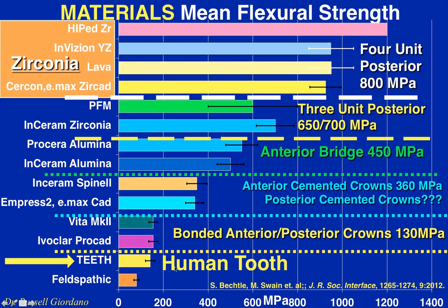What's also very interesting is that if you start looking in the literature and your criteria for materials is just strength, human teeth are not sufficient with respect to strength to be used in the mouth. So the conclusion that we must draw is that we must extract all teeth and replace them with titanium implants, because we all know that implants are much, much more reliable than teeth. At least that's what I hear from the implantology people and at the school. Of course, the endodontists have a completely different opinion. They think we should save every tooth. The periodontists who used to like to save teeth now are in favor of ripping them out and replacing them with implants. So if we use our strength criteria, human teeth are not strong enough. And here's the reference down here if you'd like to look it up.